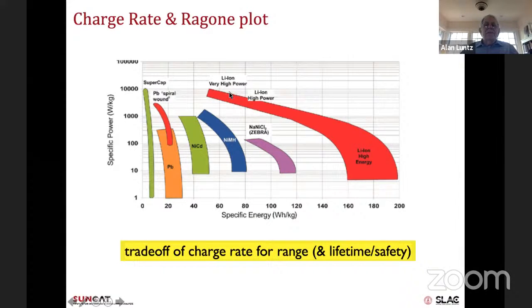So in fact, you can make a lithium ion battery which has very high power density and very high charge rate. However, you don't have much energy density. And so most people, because they want range, concentrate in the range where the energy density is high but the power density is much more modest. Charge rates are more modest. And that's a fundamental trade-off that you have to make with this chemistry.